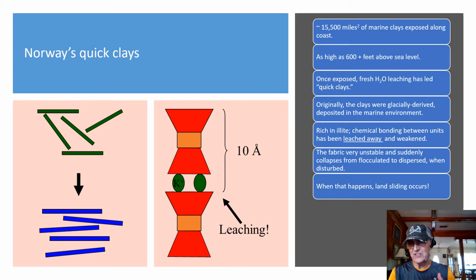The main clay mineral is illite, shown on the diagram here, where the units are bound together by potassium cations. So these illite clays have been leached. In other words, the cations that bound these units together have been leached away, and therefore the fabric has been weakened. So the fabric is now very unstable, like a house of cards, and it can suddenly collapse from a flocculated into a dispersed arrangement when disturbed. And when that happens, you have problems.